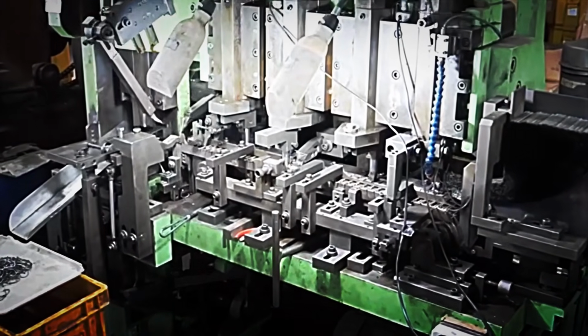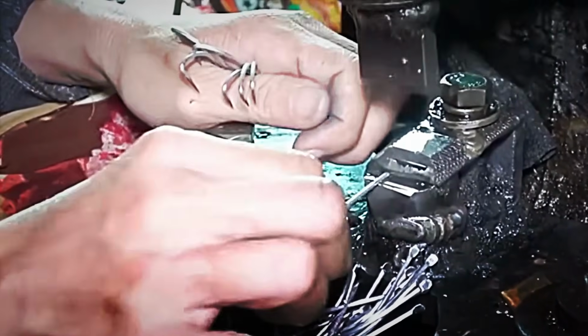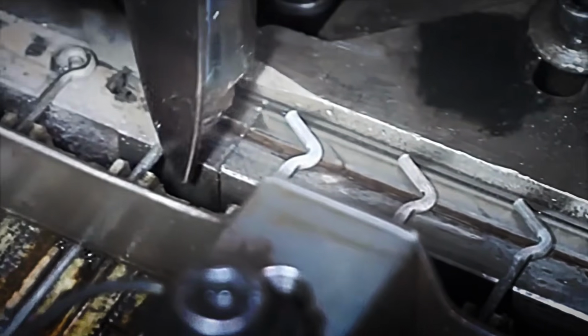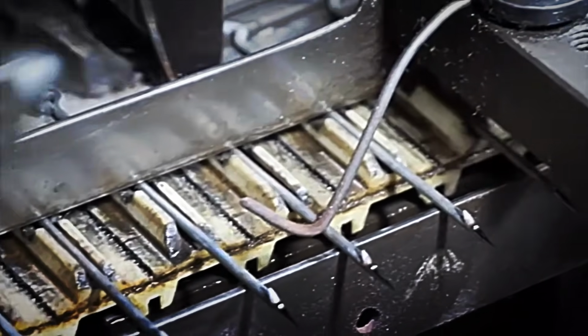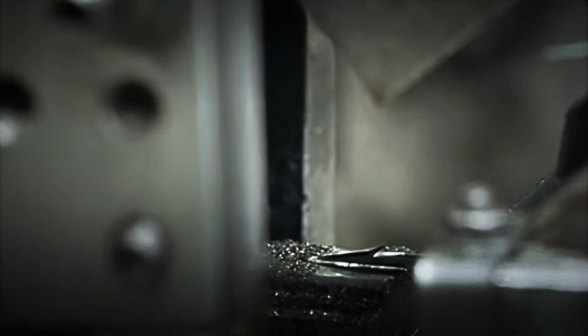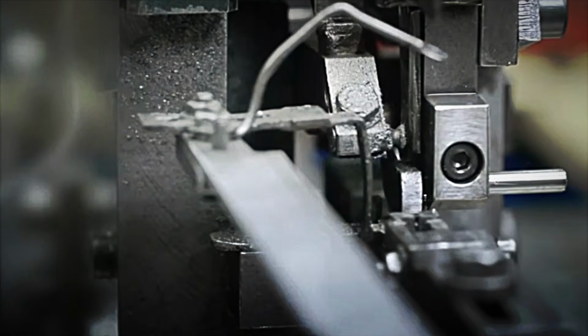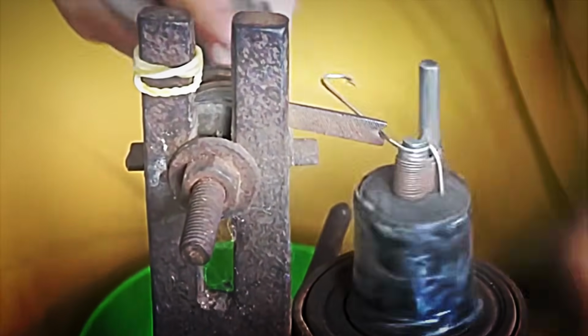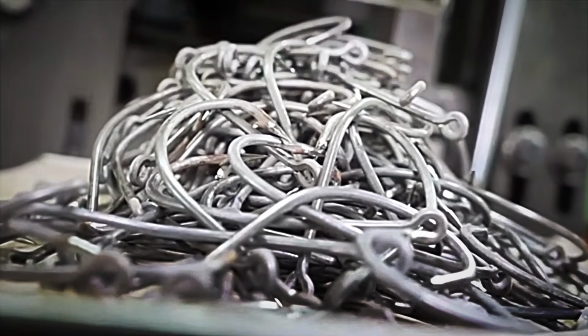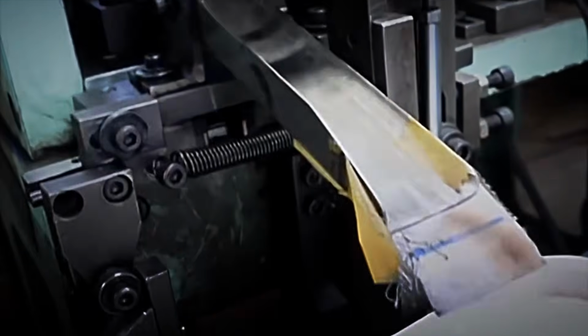However, quality control is not limited to appearance alone. To verify the product's actual strength, technicians randomly select samples from each batch and subject them to mechanical testing. In these tests, the hooks are placed in specialized machines that gradually apply tensile force. The load increases progressively until reaching the level of stress for which the hook was designed. The goal is to confirm that the metal maintains its shape without deforming and that no unexpected fractures occur under tension. This type of testing ensures that the heat treatment and the steel's composition have produced the correct balance between hardness and flexibility, a combination essential to prevent the hook from breaking or bending during fishing.